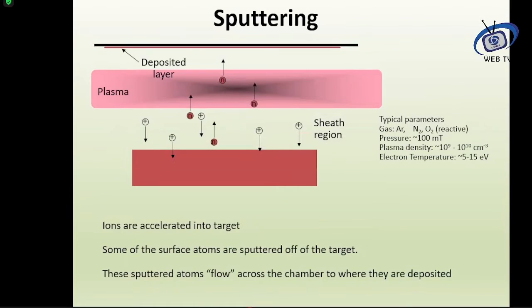The other part is this system, where we have the substrate, and this is the plasma. This is another electrode. The ions are accelerated into the target, and some of the surface atoms are sputtered off the target, and these sputtered atoms flow across the chamber, and they are deposited onto this substrate. So this is the basic sputtering phenomenon.